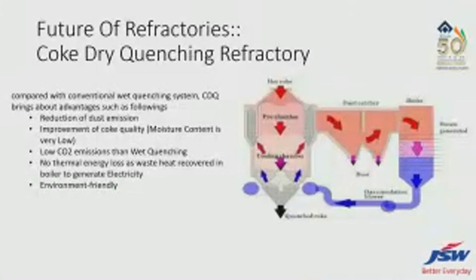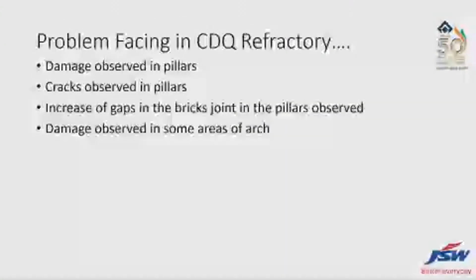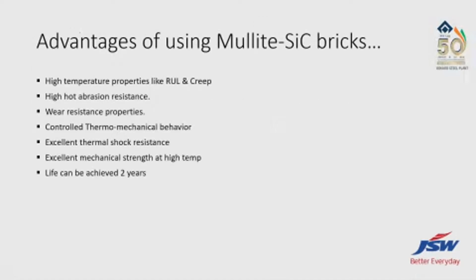It's also environment friendly. Actually, with normal fire clays, we face a lot of difficulty in CDQ. A lot of damage happens in the pillar zones and in the arch zone also. What we have decided, we are going for mullite silicon carbide bricks for the pillars and arch. It has very good thermal properties, excellent mechanical strength at high temperatures, and hot abrasion resistance, and we are expecting a life of 2 years instead of 1 year with the regular fire clay bricks.